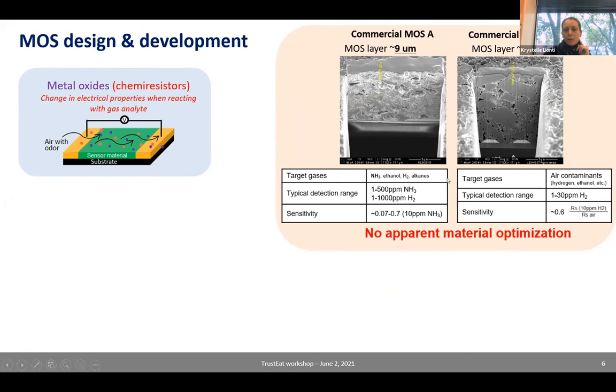And we were actually surprised to see that, except for being really thick, which is not such a good thing for gas sensing because it's mostly based on surface reactions. So it's not a good thing to have 10 microns between where the gas sensing happens and where the electrodes are. So except for being both pretty thick, they're very different. One looked very amorphous, the other one looked more crystalline. One looks pretty dense, the other one has a lot of big pores in between. So it became pretty clear that there was still a lot of room for a material optimization to boost the